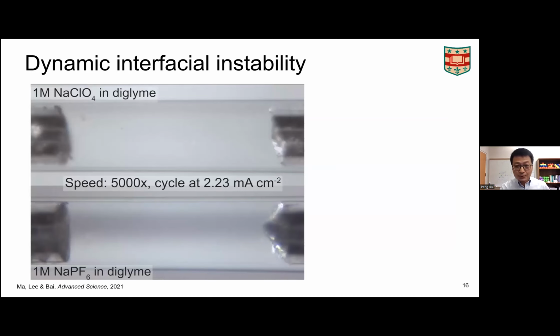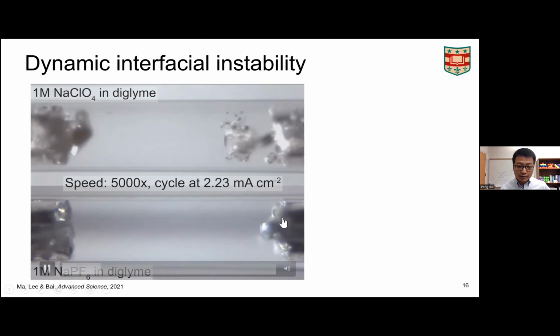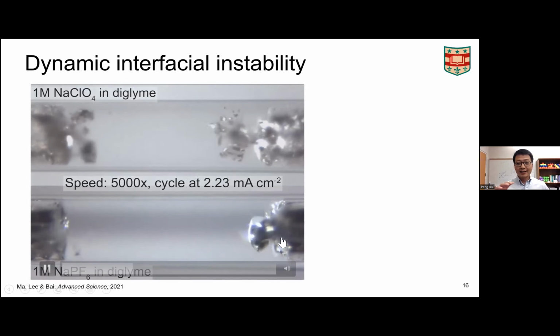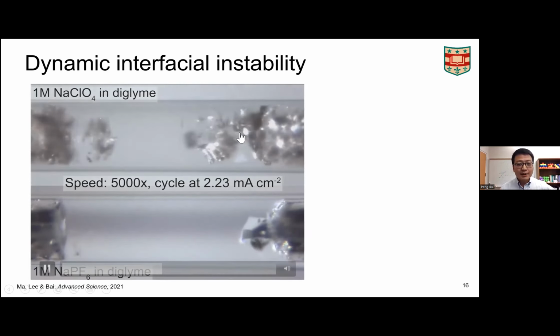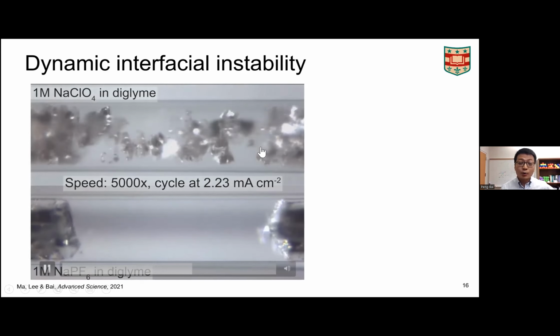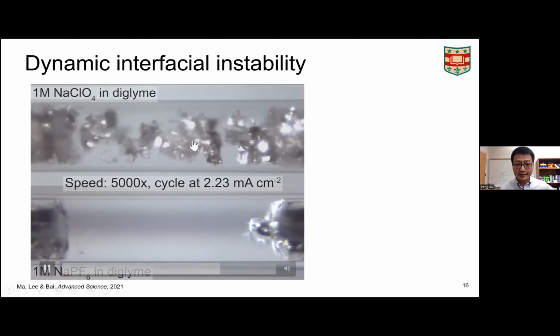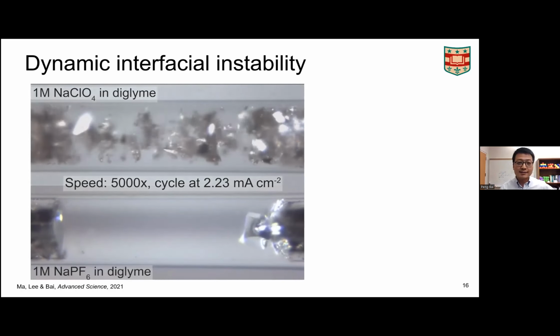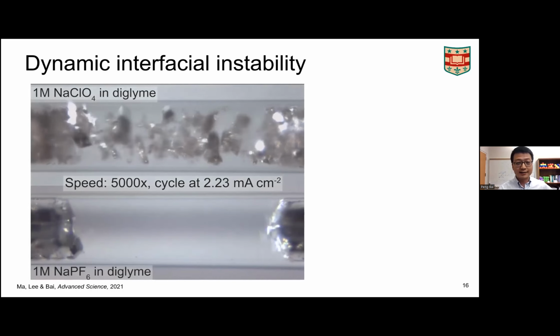Because here are two videos I want to demonstrate. The top one showed you a not so good electrolyte. It is still compatible with the metal electrodes. And this is the good electrolyte we prepared. And we are doing the cycling, charging, discharging, deposition, dissolution, plating, or stripping. But you can see that for the good electrolyte, you always have this kind of shiny crystal-like structure, right? But for the not so good electrolyte, you quickly generate this kind of residual structure, like the whiskers we demonstrated in the lithium system, right? And that is apparently not so good.